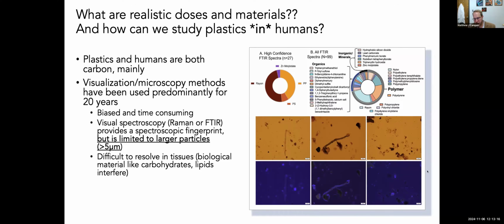These are really nice assays to use, but the problem is a lot of the systems don't even reveal particles less than 5 micrometers in diameter. As somebody who studied air pollution all my life, I know that PM 2.5 is the standard globally. So we don't even worry about something unless it's smaller than 2.5 micrometers. And of course, the University of Rochester made a big case, a very important case, about ultrafine particles, which are 100 nanometers. So we knew that we had to look at something smaller.